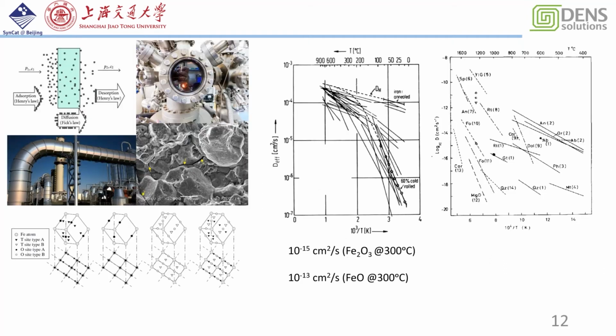Also, another problem we have to consider, which is rarely discussed in any reference, is the penetration of hydrogen. Penetration of hydrogen inside metal is well known in construction, because it will cause hydrogen damage to the metal and to the instrument. But this information has never been considered for hydrogen reduction, because people always think the diffusion of hydrogen inside the bulk is very slow, but somehow it's not. Based on calculations, the diffusion rate is quite high, even not in the metal but in the metal oxide. So it will play an important role in the reduction of the iron oxide.